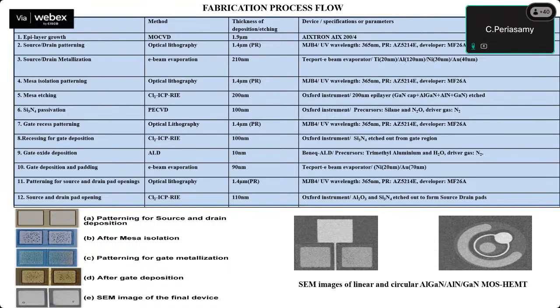Okay, so we have studied two different structure topologies. One is linear, and the other one is a circular pattern. For gate oxide deposition, we have used the aluminum ALD technique, atomic layer deposition. For the gate deposition and the padding, we have used E-beam evaporation, because we know that the electron beam evaporation method is suitable for depositing metal.